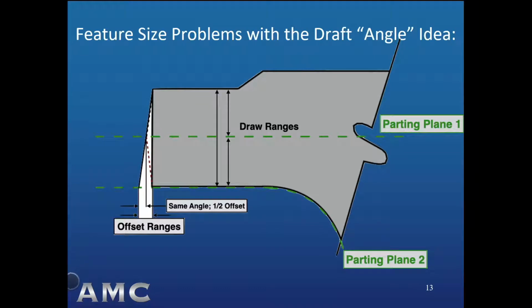Let me explain why. Here we see an as-cast surface on the left end of a casting that has two molded parting plane options. One option has the casting split through the center, and the draft angle creates an offset that is the same on each side of the casting end feature. The second option has the parting plane following the bottom surface of the casting. The same draft angle now creates an offset that is twice as large as the offset created by parting plane option 1.